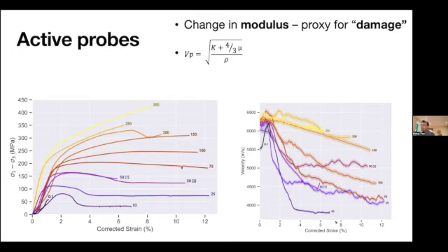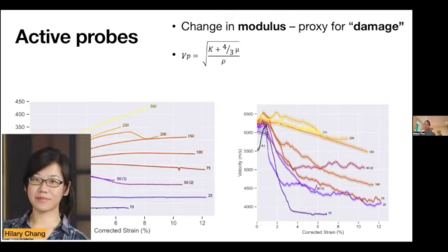And so as you can see, at low pressures, for example here 10 MPa, we have a huge drop-off in the velocity, where we go from about 6 kilometers per second to below 4 kilometers per second, that then stabilizes. Whereas as the pressure increases, this decrease becomes more linear and much less pronounced. So there is less damage that would slow down the P waves as they go through the samples. And this has been analyzed extensively by Hilary Chang, who did a really great job by getting very precise measurements.